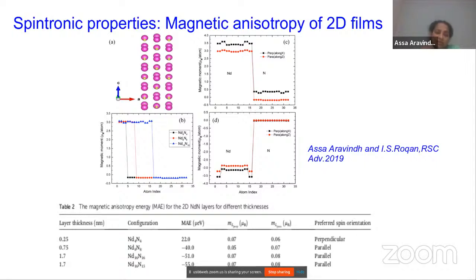So in this particular example, we studied two-dimensional neodymium nitride layers, which showed very nice magnetic anisotropy with perpendicular anisotropy. And perpendicular anisotropy is more favorable for perpendicular magnetic storage devices. And this is a purely theoretical study, which can guide experiments to attempt such kind of synthesis or further XMCD or magnetic dichroism studies, whatever they can do, and verify it. And these are very much commercially important materials also.